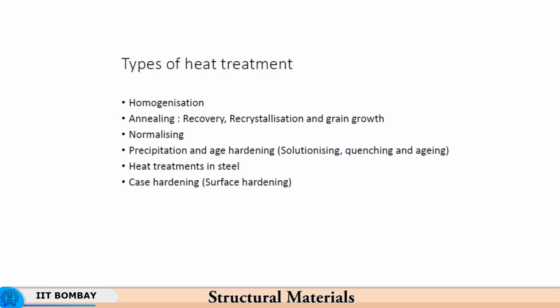So, then you have what is called normalizing. Here what you do is you again heat the material to a relatively high temperature and then leave it in the air. So, normalizing is basically air cooling. So, it all depends on the ambient temperature of the air. If the ambient temperature of the air is as per summer, you will have one rate of cooling, in winter you will have another rate of cooling. So, if the climate is extreme, then you can have significantly different cooling rates in the normalizing condition, because in winter it will cool faster, in summer it will cool much slower.